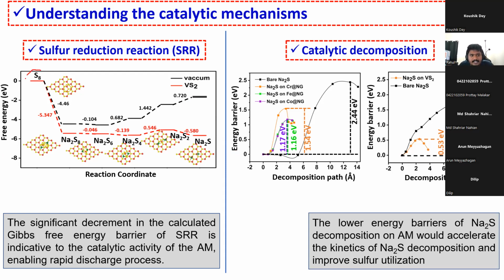And as I previously told, during discharge, S8 will convert to Na2S8, Na2S8 to Na2S6, Na2S4, Na2S2 to Na2S. This is the final discharge product. When we talk about this conversion in the vacuum or without any catalyst, you can see that among all the steps, this step has the highest value. That means it is the rate determining step. Basically, the step with the highest value is the rate determining step or the most endothermic step in the overall reaction.